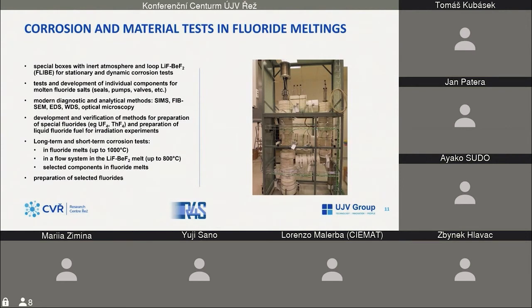These tests are providing the individual components for melts of fluoride salts, and we are developing and verifying methods for preparation of special fluorides and preparation of liquid fluoride for irradiation experiments. Our loop and special boxes enable us to provide long-term and short-term corrosion tests in fluoride melts up to 1000 degrees C.